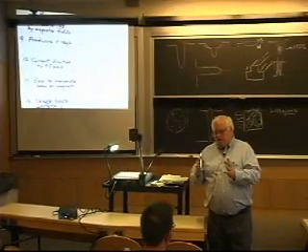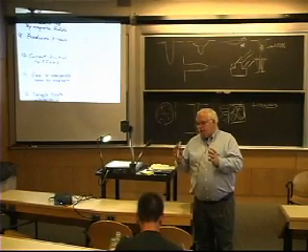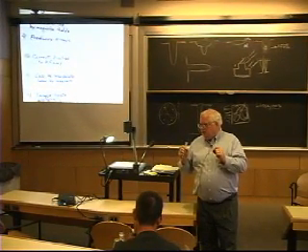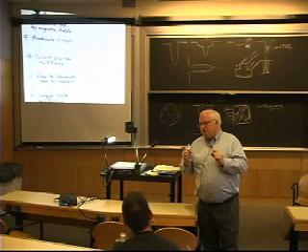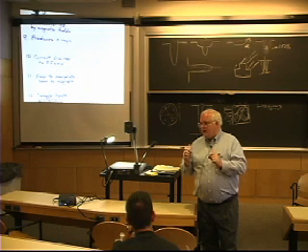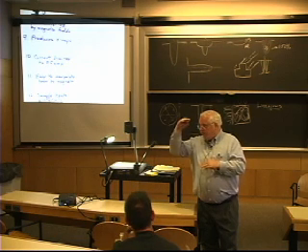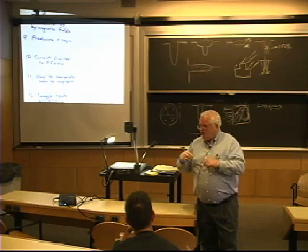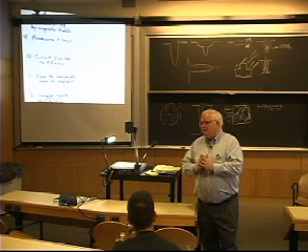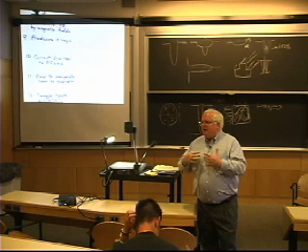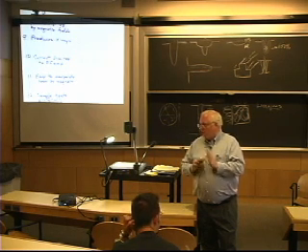Some of the really interesting things nowadays, Professor Yoel Fink here developed a perfect mirror. It is theoretically perfect because he basically puts on different layers of materials with different refractive index, and he can get reflections that are required quantum mechanically. Just like you can only have certain energy levels of electrons in an atom, it turns out there's certain things when you talk about reflection of light. If you have layers of different refractive index material, you can have certain wavelengths that are not permitted to pass quantum mechanically, okay?